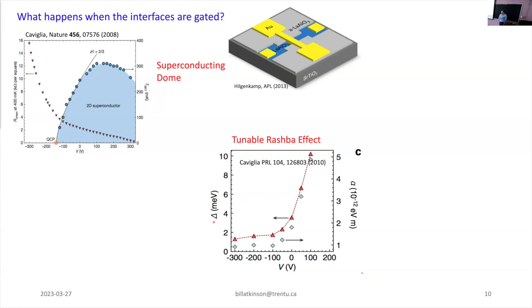And I saw a very interesting talk at the APS a few weeks ago at the March meeting, where somebody had actually put a ferromagnet on top of an interface like this, and they were driving a spin current into the interface, and then they were getting spin charge conversion through the Edelstein effect, and they were getting high efficiencies. The only downside is you have to do this at sort of 1 or 2 Kelvin.